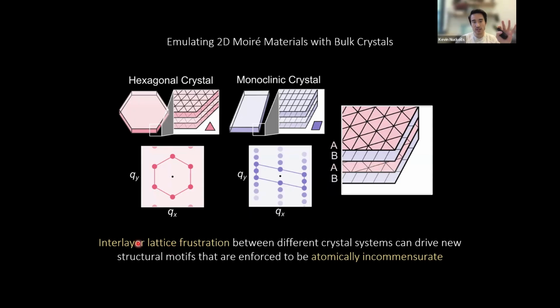And so essentially what we're doing is we're leveraging interlayer lattice frustration between these two different competing crystal systems in order to stabilize and enforce atomic scale incommensurability in thermodynamic equilibrium. I'll actually be able to grow this. This is a really great tool because there's basically no reason that I should be able to reach into a high temperature furnace and pull out twisted bilayer graphene. It has no symmetries. There's no reason why this would be energetically stable. And yet, here is an alternate route to trying to stabilize atomic scale incommensurability in something that actually could be thermodynamically stable.